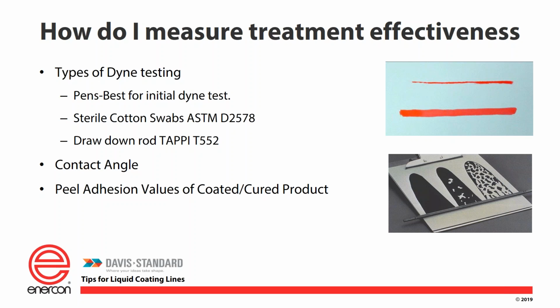of dyne solution. And some of you may have never thought of this, but for those of you who have tried the cotton swab method, that ASTM method, you have practical experience and know that if you load up that cotton tip swab with too much solution, you can kind of get the dyne number to be whatever you want it to be. Because it's got so much solution and the solution is solvent based. So if you're not mindful of what you're doing, you can get that to give you the wrong answer. On the other hand, if you're using a drawdown rod or a Meyer rod method, it meters that dyne solution uniformly all at the same time, and you can see instantaneously